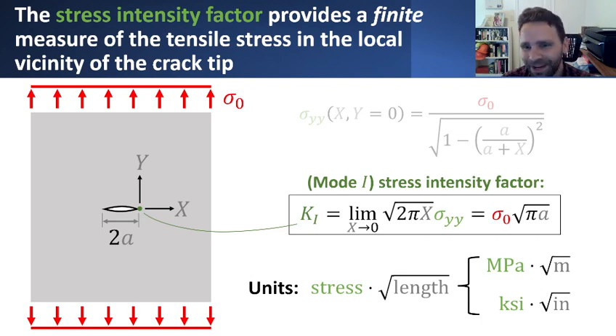But in any case, rather than trying to measure what's happening in the local vicinity of the crack as x goes towards zero, we know we can't really measure what's going on with the stress because it's going to be infinite. But we can measure this thing. In the limit as x goes to zero, we'll get this finite value. And it so happens that this finite value that we obtain from this limit has a specific name. It is called the so-called stress intensity factor. And I'll be even more particular. I'll call this the mode 1 stress intensity factor. You'll see why in a minute.